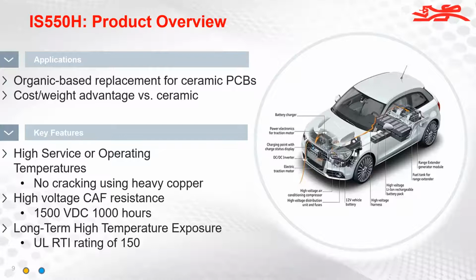Yep. So I'm familiar with ceramic PCBs. I don't know if folks on this call are aware, but Insulectro supplies the ink, the sintering inks, and some substrate materials like green tape, which sinter at 850 Celsius. And they have their applications because there are certain environments where you have to use a ceramic material. You can't use an organic material. But there's a big space that's not being filled, that it's not suitable for FR4. Used to be kind of the domain of polyimide, but there's a need for something new, and that's what this is all about.